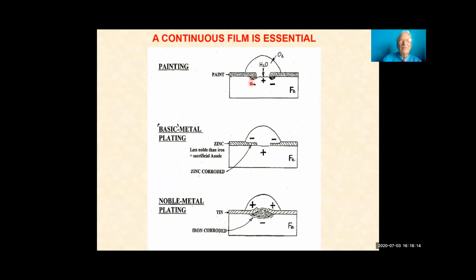On the other hand, if you have something that is sacrificial to iron, that is, it naturally has a lower electropotential level, if you put that on the surface, this negative area of corrosion occurs on the coating, on the zinc, not on the parent metal. And so this is called a sacrificial coating and is an extremely good way of protecting iron, even if it's got holes in it. I won't take time to show you that, but that's the tin plating is exactly the same problem as paint coating.